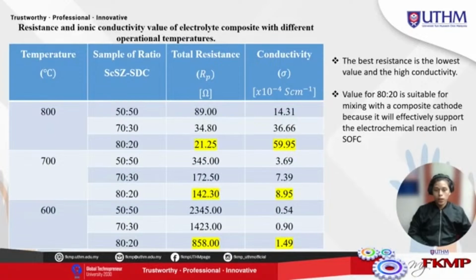From the EIS testing, we can also calculate the resistance and ionic conductivity. The results show 80-20 is the best over all temperatures. The resistance at 800 is 21.25, at 700 is 142.30, and lastly at 600 is 858.00. And then the conductivity at 800 is 59.95, at 700 is 8.95, and lastly at 600 is 1.49. The best is the lowest resistance and the highest conductivity.